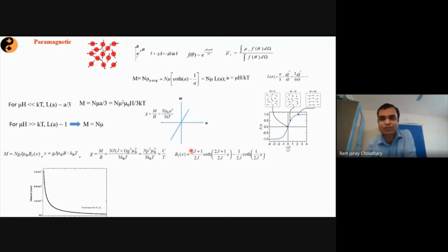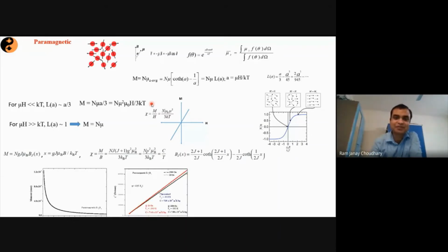Okay. Now I'll just show you some typical examples of paramagnetic material and whatever I have talked about. See, this is one of the Er2O3 samples which we have measured, and you can see that if we lower the temperature, the magnetization keeps on gradually increasing. And this is consistent with this kind of expression where your magnetization is inversely proportional to temperature, right? Okay. Now it also tells us that if I plot this magnetization with respect to 1 by T, we should have a straight line behavior, right? See, this is the straight line behavior, okay? And these measurements are done at 2 different fields. That's why you have 2 different slopes, okay?